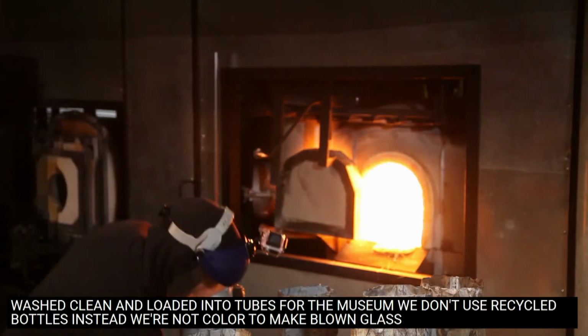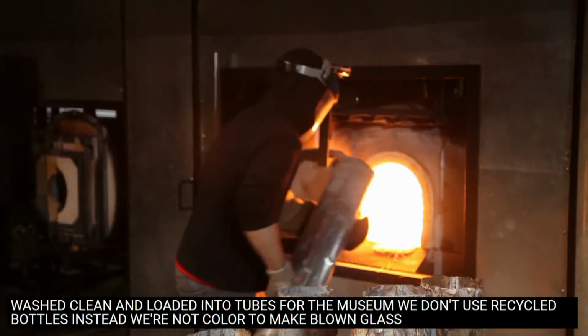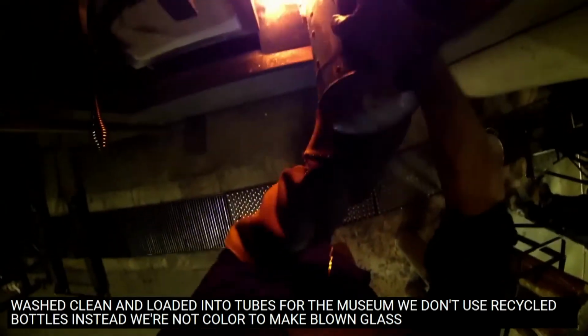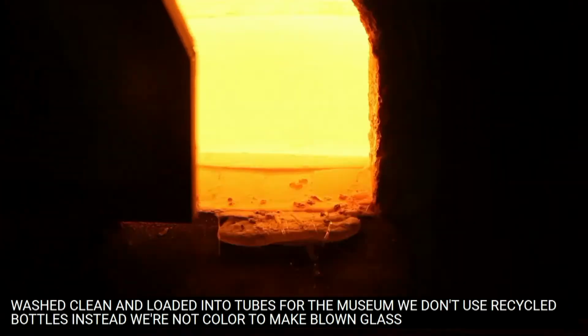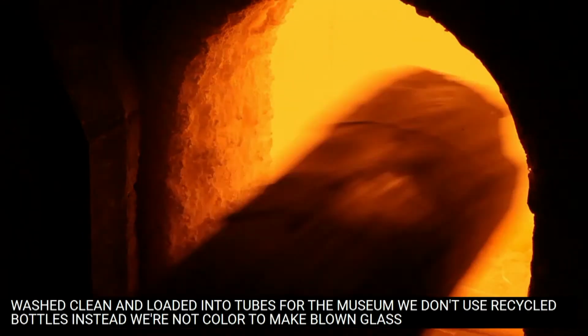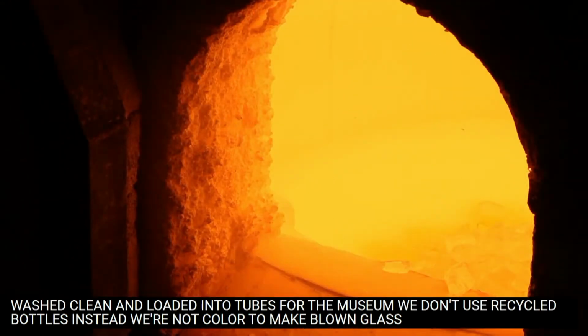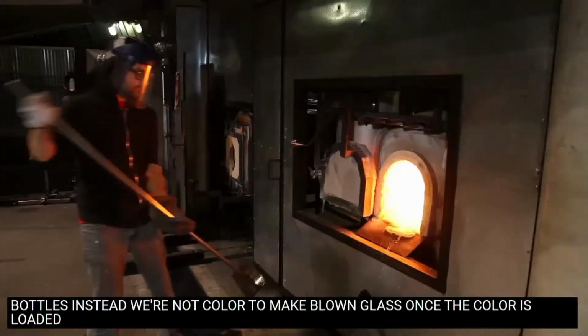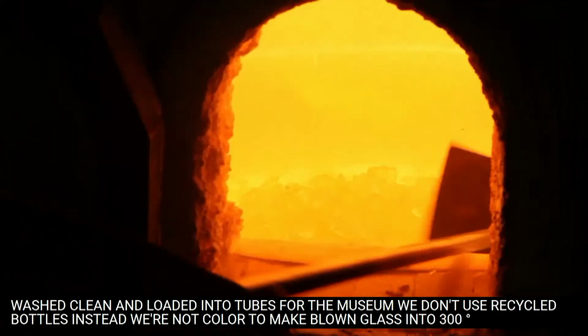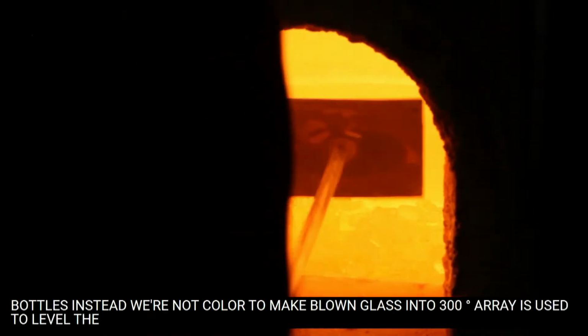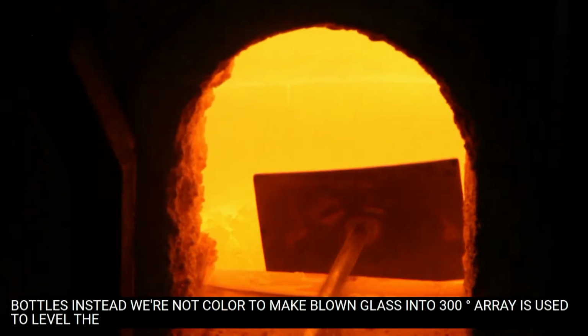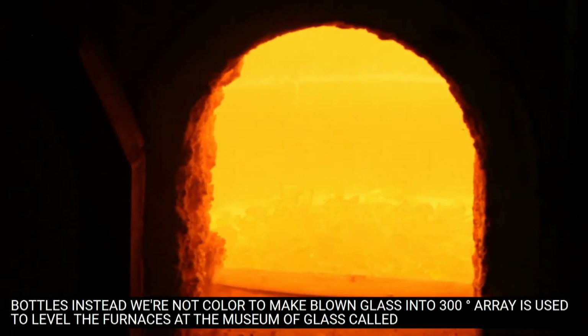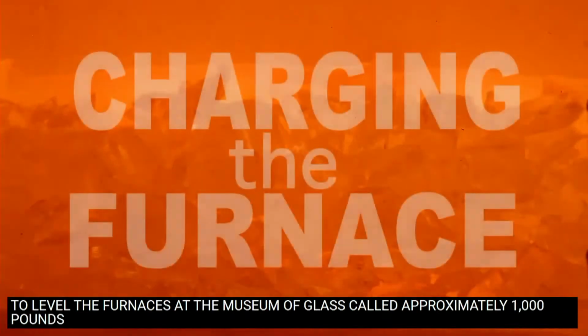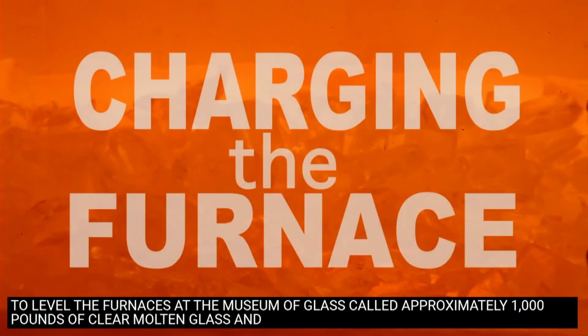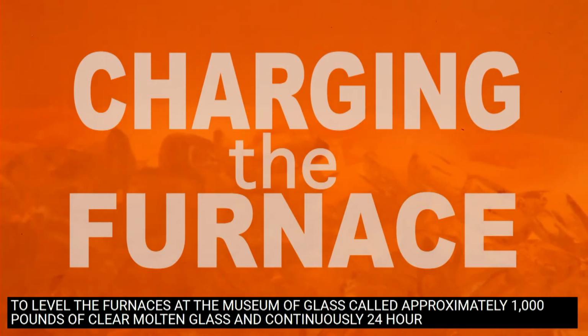The primary ingredient in glass is silica sand, or silicon dioxide. The other two main ingredients are soda, or sodium oxide, which lowers the melting temperature, and lime, or calcium oxide, the stabilizer. Once the cullet is loaded into the 2300 degree furnace, a rake is used to level the glass for even melting. The furnaces at the Museum of Glass hold approximately 1,000 pounds of clear molten glass and run continuously 24 hours a day, 7 days a week.